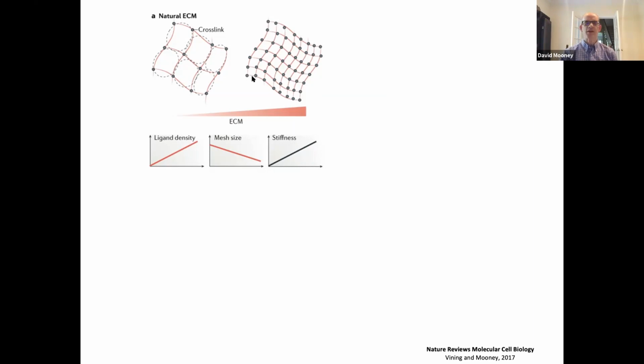Now this works quite nicely. However, as you add more of the polymer, you also change how cells engage with the material because these natural polymers are ligands for cell adhesion. So you increase the adhesivity of the system in concert with the stiffness, and you also decrease the mesh size, which may be very important in mediating diffusional transport of macromolecules like growth factors that are really important in the cell biology.